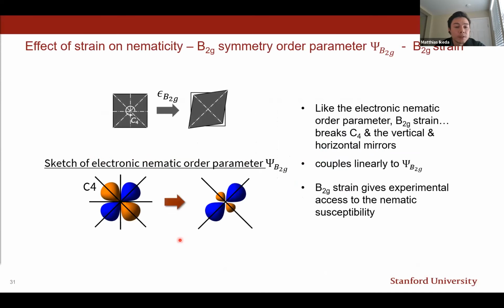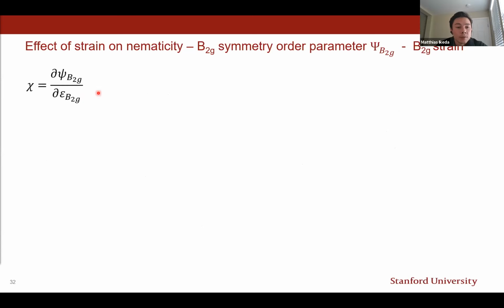And in this case, we need to apply uniaxial stress along the tetragonal 110 axis such that we induce a B2g strain component. And B2g strain, as we know, breaks the same symmetry elements as the electronic nematic order parameter at the nematic transition. And so it is for that reason that through elasto-nematic coupling, B2g strain actually induces nematic order. Now, if we had a way to measure the amount of order introduced and the amount of strain used to induce this order, we'd be able to get a measure for the nematic susceptibility.